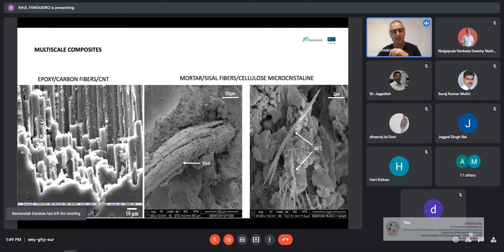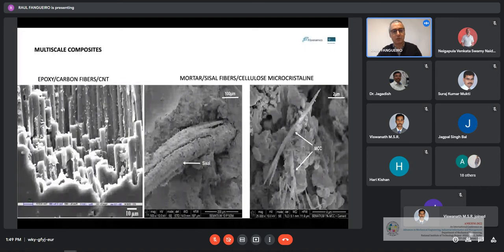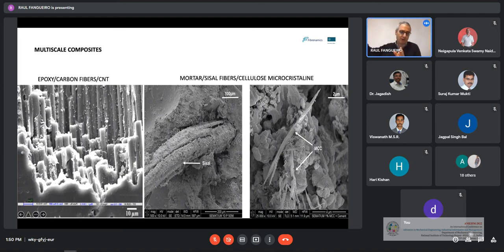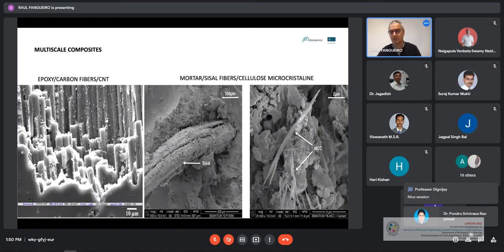So it means that we may have, as you can see here, these axially oriented, completely parallel elements that are carbon fibers. But then we can improve the properties of this composite, impregnated with an epoxy matrix, by functionalizing this material with carbon nanotubes in order to enhance the mechanical properties, in order to give electrical properties to this material, and to put it working as a sensor, for instance, but always with a multi-scale approach. But we are doing this with polymeric matrices, but also with cementitious based matrices. This is possible as well.